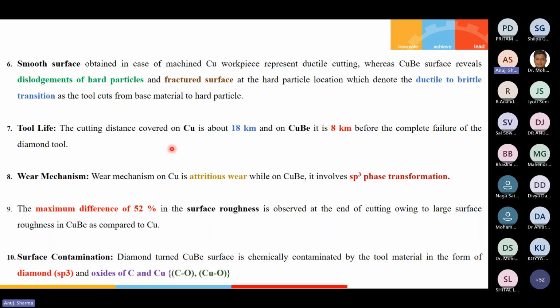If we compare the tool life, the cutting distance covered on copper is 18 kilometers, whereas it is 8 kilometers in the case of copper beryllium. So copper beryllium causes more tool wear. The wear mechanism is atom by atom, called attrition wear, in the copper material, whereas in the case of copper beryllium, there is phase transformation of the diamond to an amorphous layer.